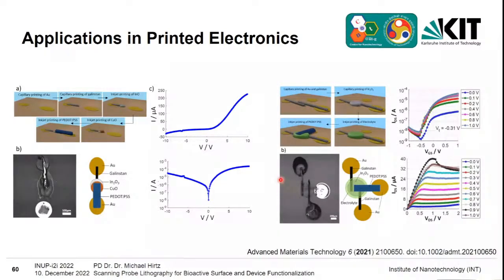We showed here already that you can have applications in printed electronics with it. So, for example, you can print diodes or transistors with it. And here the liquid metal is used for connecting the other functional materials. You can combine it with conventional printing methods like inkjet printing, but you can also deposit the other materials with capillary printing. So for example, here the indium oxide is also deposited with the capillary printing.